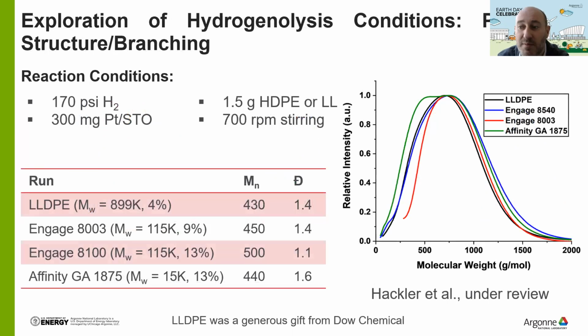What about the chemical structure of the polymers? As I mentioned before, we have multiple structures, multiple chemical compositions of polymers. What we did here was moving from HDPE, but we want to look at the effect of branching, because a plastic bag, for example, has this long and short branching. These are commercial products, you can buy this one from Dow. And what we show is that using this kind of catalyst, the final product is independent of the chemical structure.